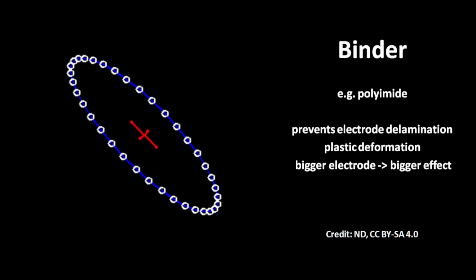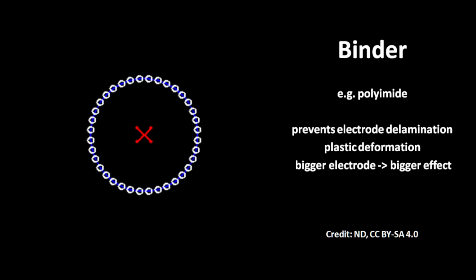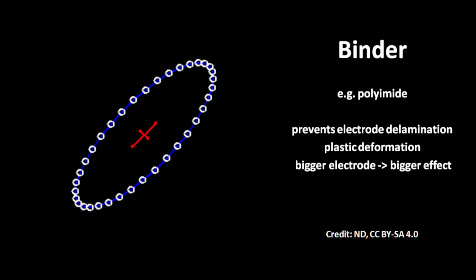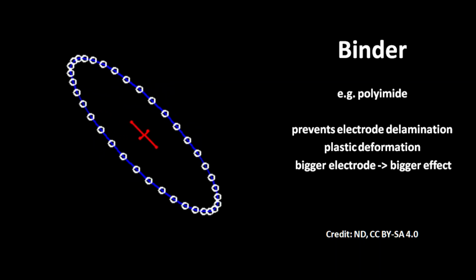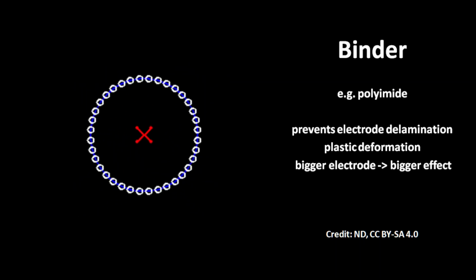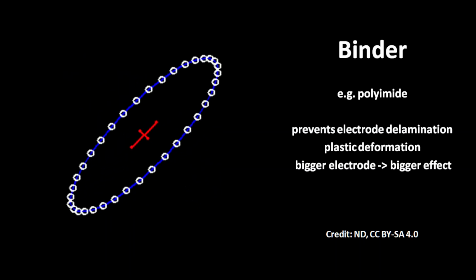The binder is an important battery component. Polyimide binders are known for their thermal stability, chemical resistance, and excellent mechanical properties. No coating delamination was found during the first cycle. However, there is a plastic deformation which is dependent on the battery size. The stretching and rippling effect is stronger at bigger electrode dimensions.